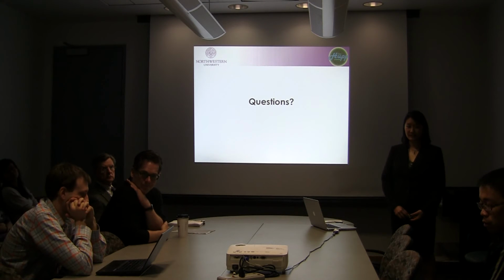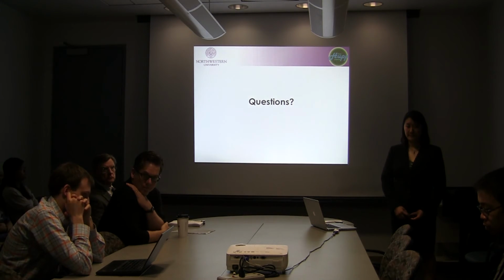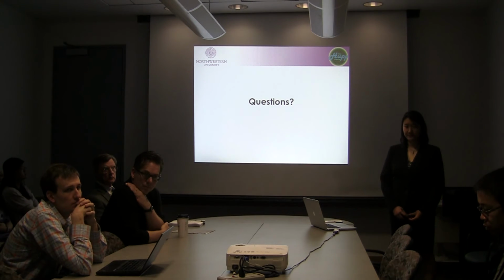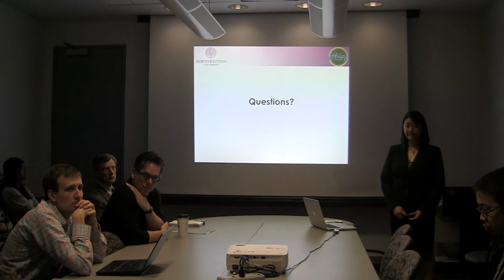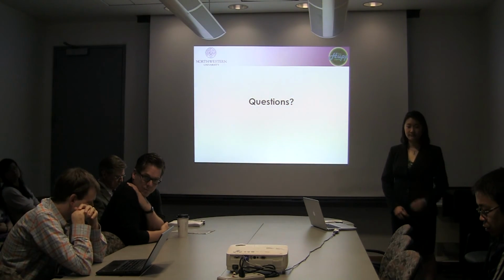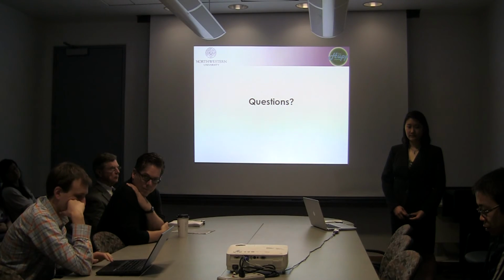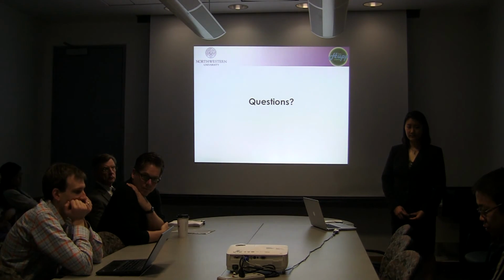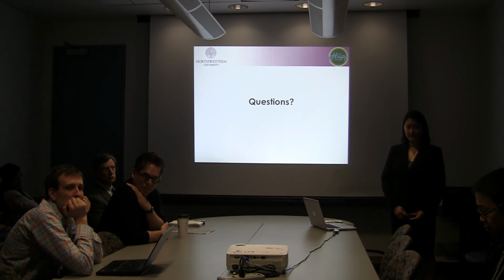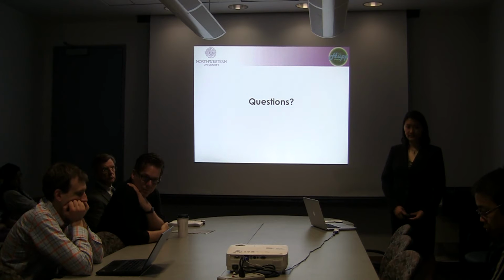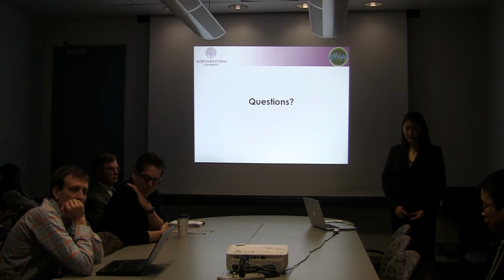to see if there are exactly zones with magnesium and those without. So I'm not in the field of MOFs, so there are some things that are not entirely obvious to me. But with this layer growth technique, I'm curious, what is the thinnest layer that's still useful, since earlier it was brought up that these start like islands on the substrate? And what is the largest thickness by which it becomes more useful to grow by the normal methods and then cut, if that's possible? I don't know if it's possible to grow a MOF and just cut it in half to get the layer that you want.